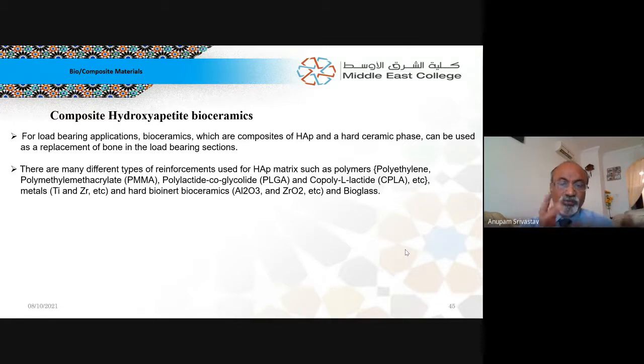So if we combine, depending on what kind of strength we have to bring in, we can improve the brittleness by increasing the fracture strength, thereby bringing all good properties. The rest of the properties are anyway there. They are lightweight, they are inert, and they do not cause any adverse body reaction. They can be easily formed into various intricate shapes, but the fracture strength was less. That can be improved by the second phase inclusion of particles. Even viscous phases can be added, even fibers can be added, depending upon which kind of strength we are looking for.